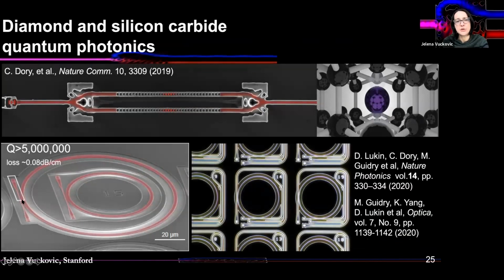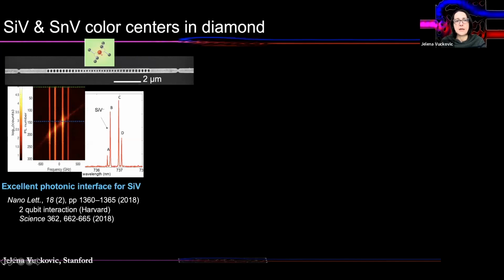We primarily work with diamond and silicon carbide. I'll mention that in a moment. And we use color centers in both diamond and silicon carbide, and we combine it with this optimized photonics on both platforms. First, in diamond, we're primarily focusing on group 4 inversion symmetric color centers, such as silicon and tin vacancy. This is just 2 missing carbon atoms and 1 extra impurity of silicon or tin in between them. And state of the art for this particular color center is that people have already demonstrated excellent photonic interfaces for silicon vacancies in diamond. There has also been demonstration of 2-qubit interaction at Harvard.